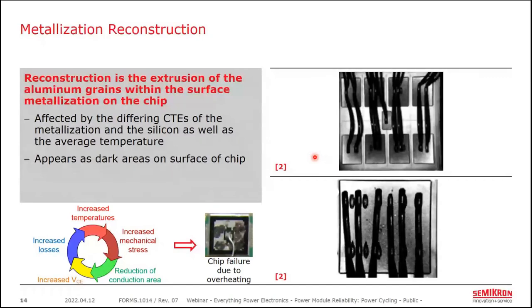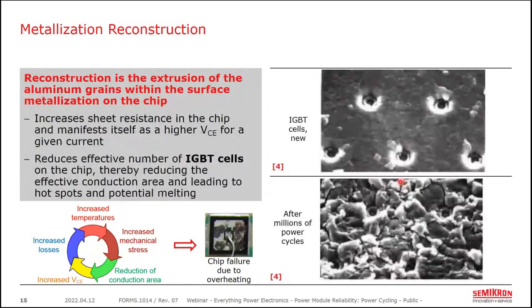The images shown here are black and white optical photos, and you can see that reconstruction appears as a darker area on the chip versus the normally shiny metallization here. So if we zoom in on that surface using a scanning electron microscope, we can see the individual IGBT cells have become distorted by the grains of aluminum as they stick up out of the surface of the chip. This is the before here, and this is the after millions of cycles.